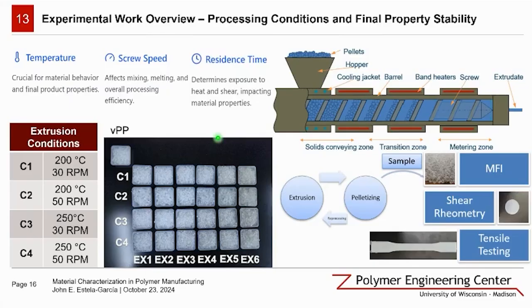Finally, residence time ties it all together. I'm a chemical engineer, so I'm looking at the extruder essentially as a chamber, a reaction chamber. And residence time is telling us how long the polymer is exposed in this high stress, high temperature environment. So this is a balancing act. We need enough time for proper melting and mixing, but not so much that we start seeing significant degradation.